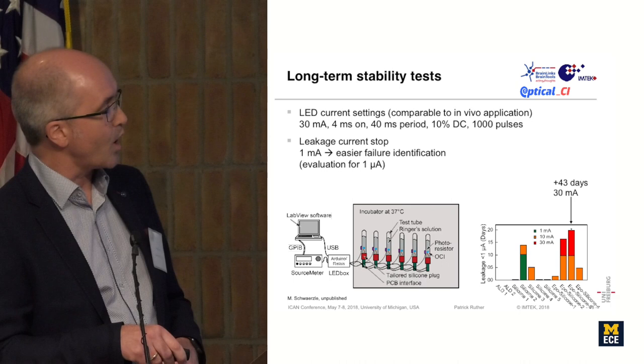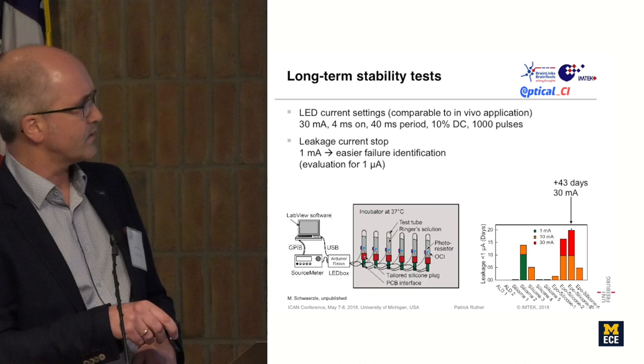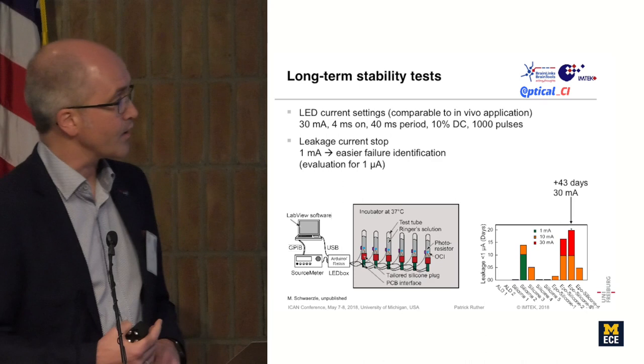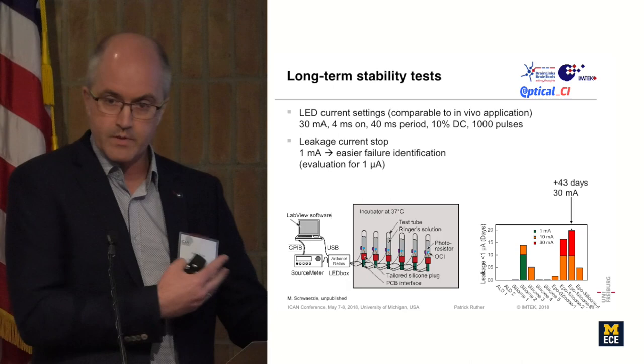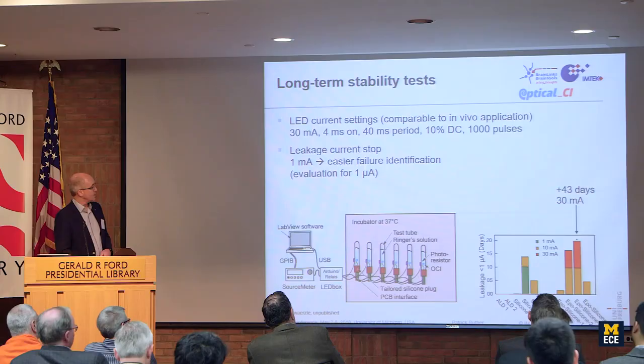Here in this case it was 10 days at 30 milliamps, and this probe survived an additional 43 days. So I would say under these harsh conditions that's more than enough for animal experiments, and that's the reason why we use these devices now also in cochlear implant tests.